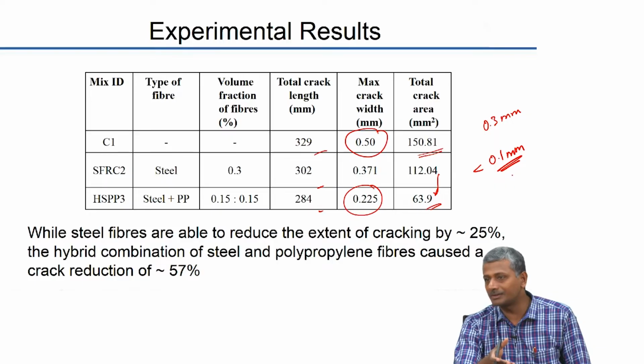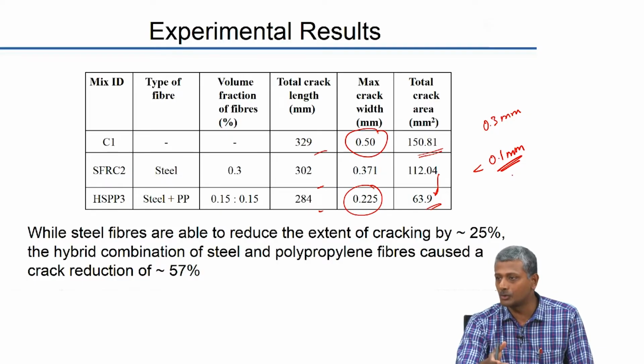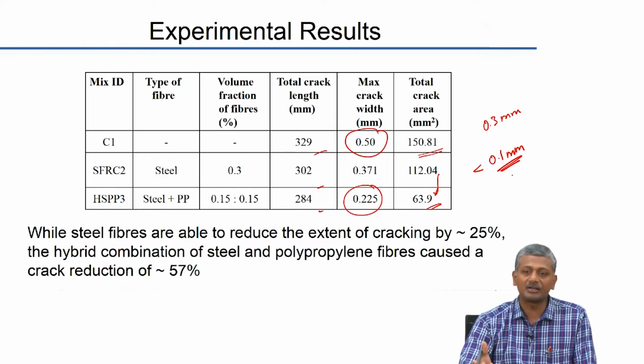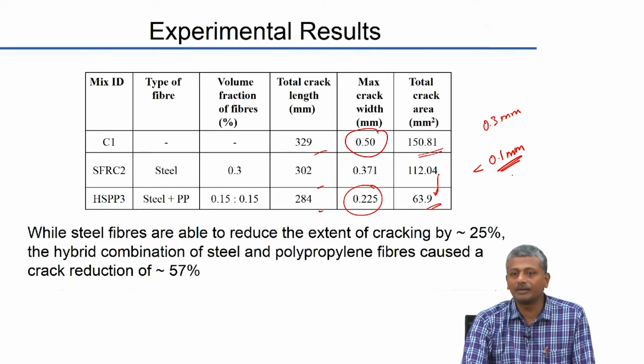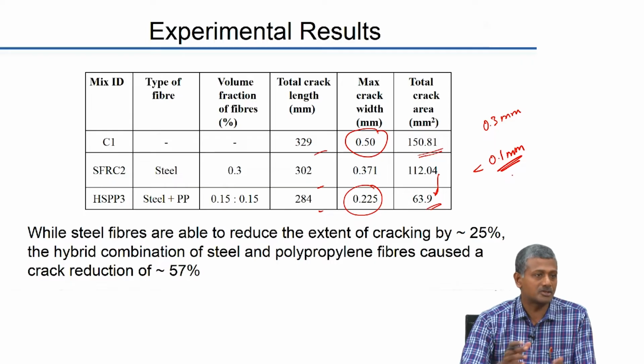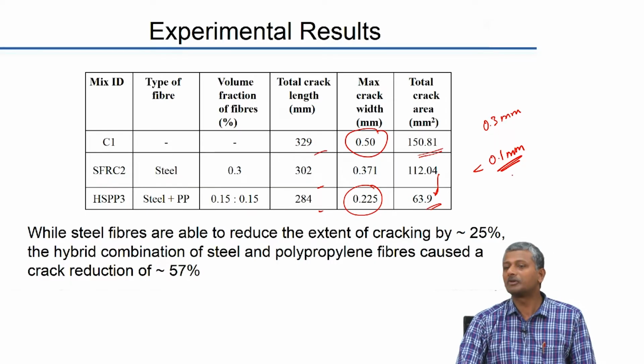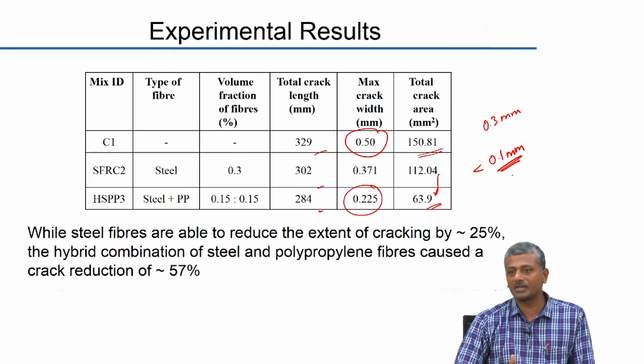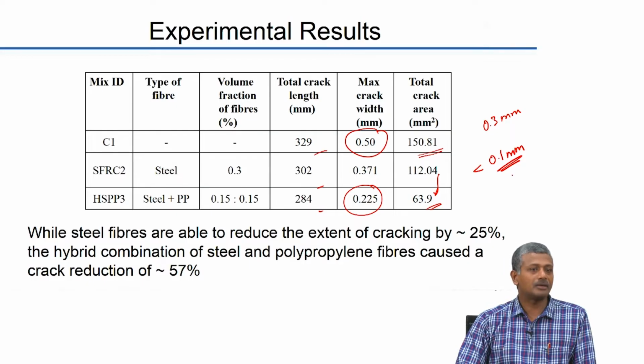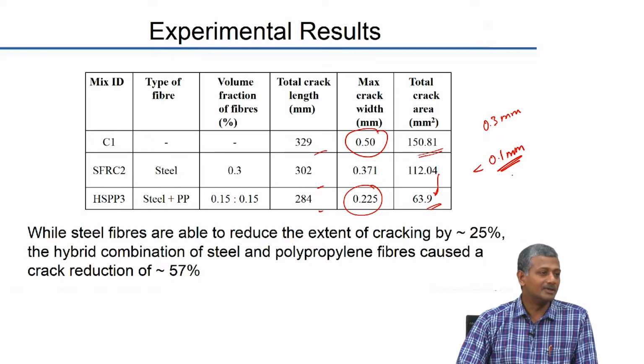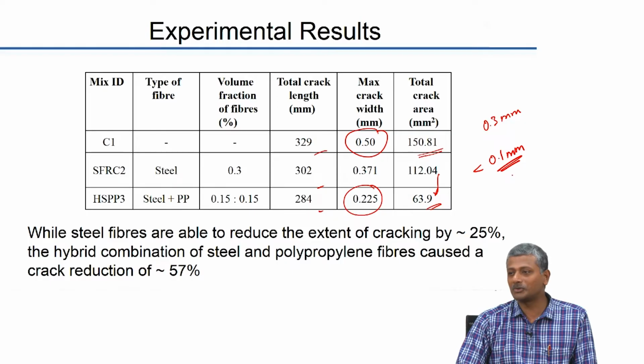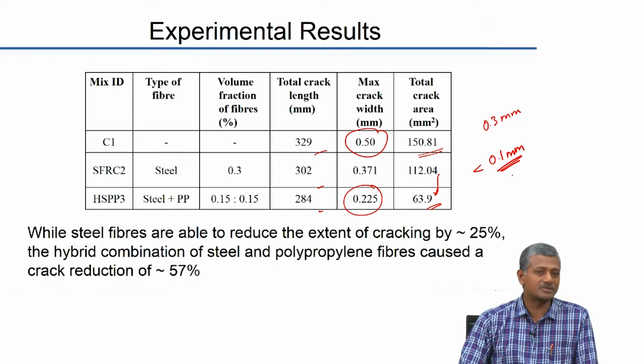For example, you saw that real life example of the metro decks that I showed you. The crack widths there were almost as much as 2 millimeters in some cases. So, if they had used fibers, it would have definitely restricted crack width even if plastic shrinkage is indeed occurring. Okay. But of course, the use of fibers is not something which is very easy, you need to justify it, it is an expensive solution. Okay. And to a large extent it depends a lot on the abilities of the marketing people, how well they are able to market their product to different construction companies, and whether they are able to convince that the use of fibers is absolutely necessary.